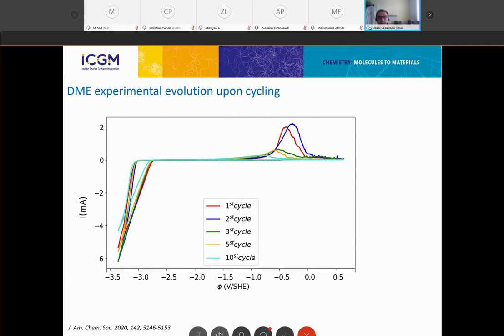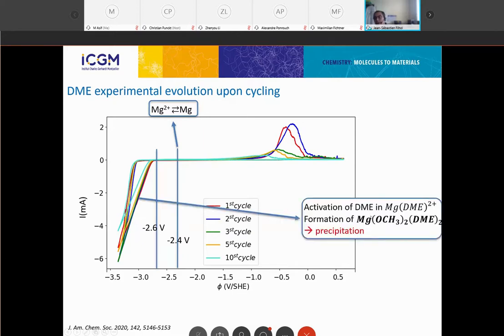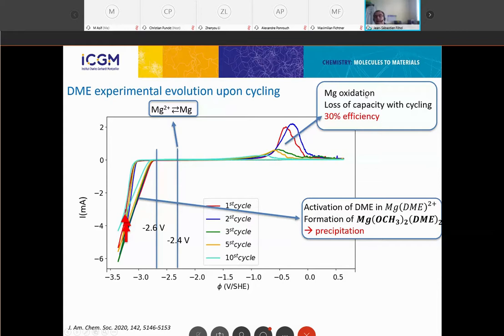So if we look at the experimental results, I've said there's a magnesium reduction. And what we see, if we look at the zone where our solvents that is coordinated to magnesium start to be unstable, we see that some kind of reduction already happens. That is certainly a mixture of magnesium reduction, but also of DME, and some kind of precipitation that is going to isolate the electrode, and we see that there's a decrease of the intensity on cycling. In the oxidation part, we also see that the amount of oxidized magnesium is quite low in comparison to the one that was formed, and we have very low efficiency, meaning that there's some kind of secondary reaction that is happening.